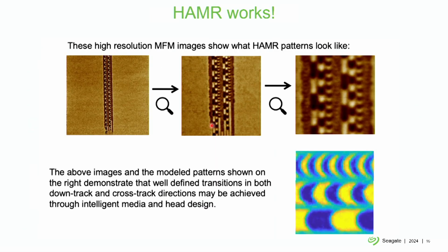These pictures were taken when nobody would believe that HAMR was a real thing. So these are magnetic force microscopy images of HAMR tracks, just zoomed in. Kind of outdated, but cool to show. And it shows a unique feature of HAMR patterns. It shows the curvature in the transition. We have a heat spot, and the heat spot determines how the bits are written. So this curved transition is a unique feature of HAMR, which is not present in perpendicular.